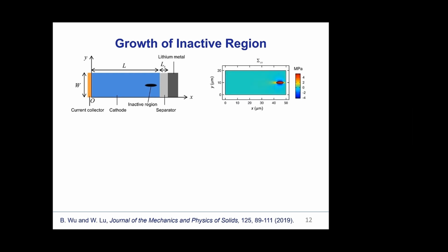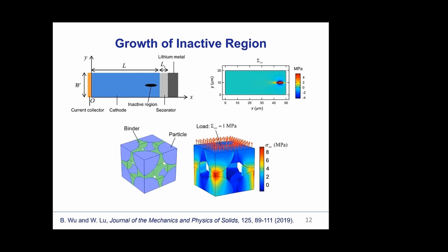We find that the inactive region can generate stress concentration. The large macroscopic stress can cause debonding between particles, leading to further growth. This suggests that such hidden damage can be important for battery applications.